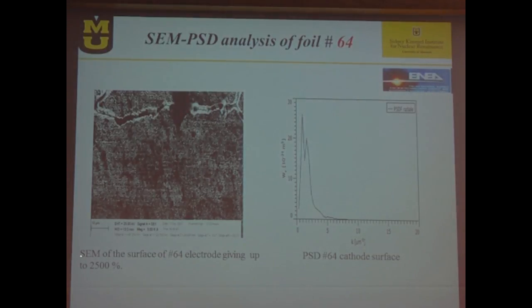So what happened, we took 64, which is the leading cathode, which was cut into so many pieces and spread all over, NRL, SRI, ENEA, and others, to try to understand what was going on. And as you can see, these are the grain boundaries, but you see a labyrinth structure. And when we analyzed the surface, this is 1 over the wavelength, or 1 over micron, and this is the x.